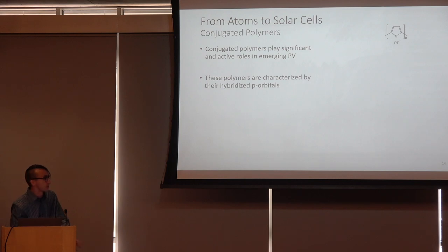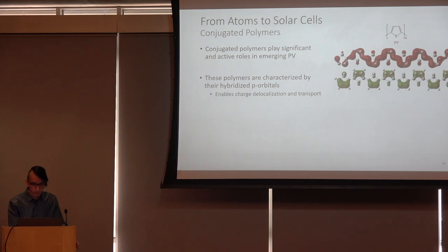And these polymers are characterized by these hybridized p orbitals, where you have orbital mixing, and you wind up with orbitals that don't just span, say, two hydrogen atoms, but actually span very significant lengths of the polymer backbone. And it's these delocalized orbitals combined with a band gap, et cetera, that lead to the particularly interesting electronic and optical properties of these materials.